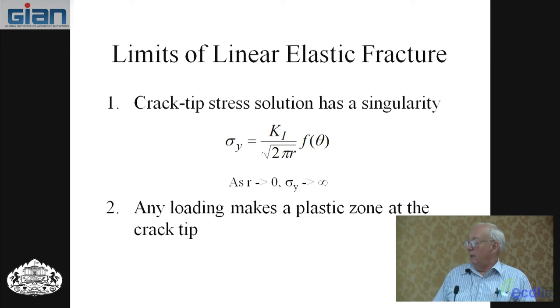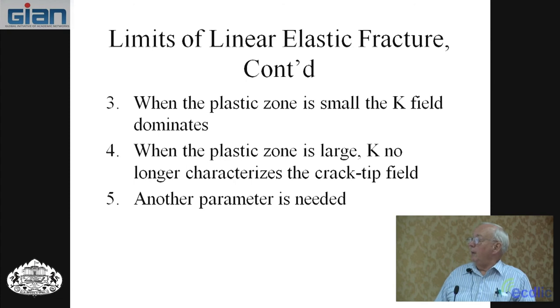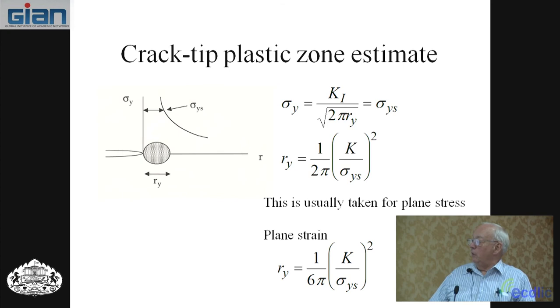It doesn't, because real materials, especially metals, can't abide very high stresses. When you get very high stresses, you get plasticity. So real materials get plasticity. So at the crack tip, when you get close to the crack tip, you get a plastic zone. And I'll show you this. This is the stress analysis as you get close to the crack tip, and it gives you a plastic zone.